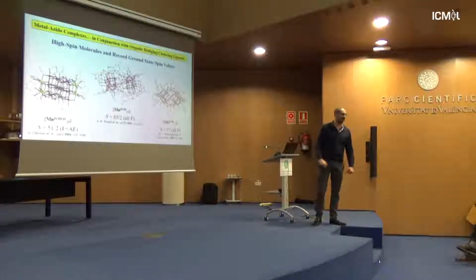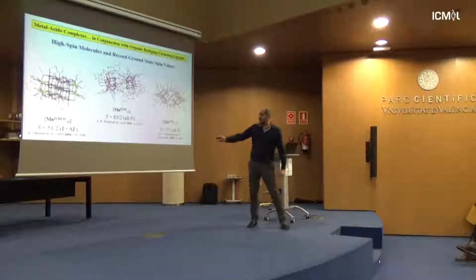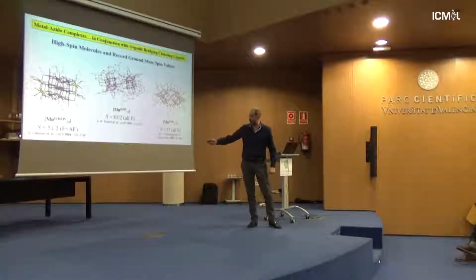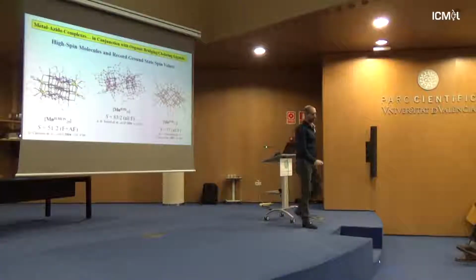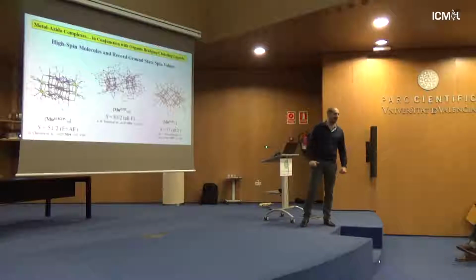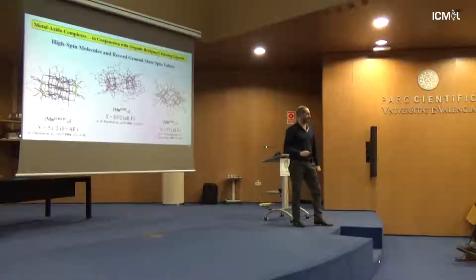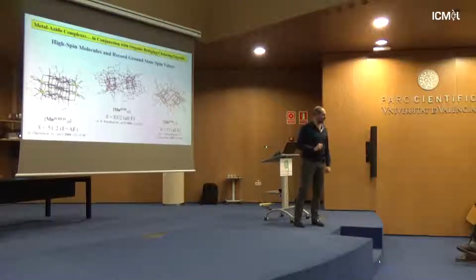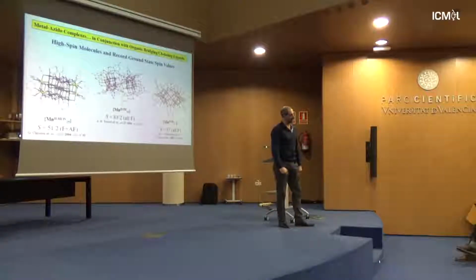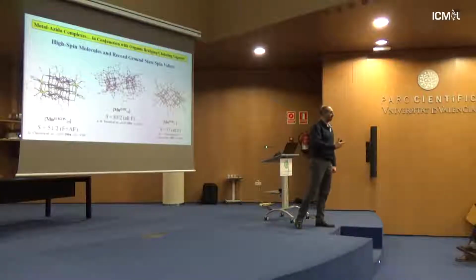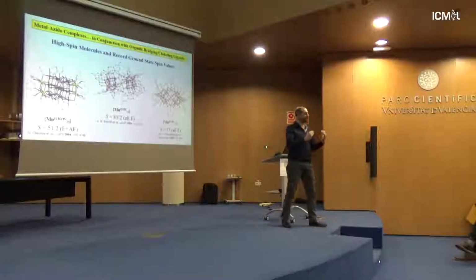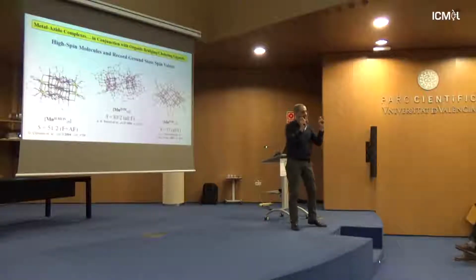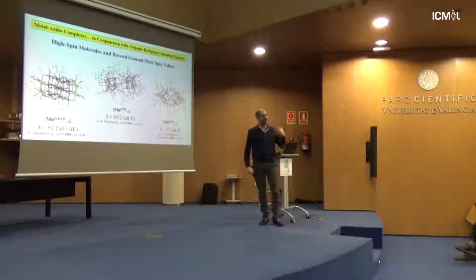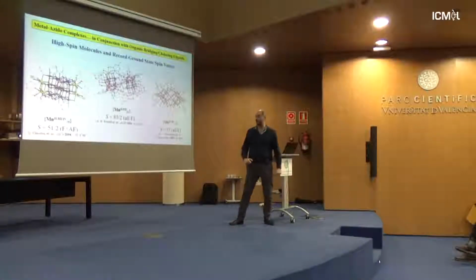These are super high spin molecules. Excellent. Even that manganese 25 compound of Christou, the first actually giant spin compound, although it has a 51/2 spin ground state, this is not the maximum possible. It's an intermediate spin given the number of manganese 2+, 3+, and the central manganese 4+ ion. If you ask me why is that, it's obviously because we have competition from many different organic components which contribute negatively to the ferromagnetic component, plus other characteristics which arise from the presence of organic ligands.